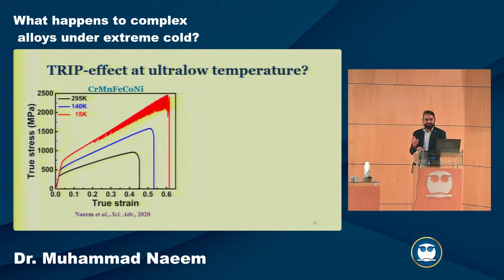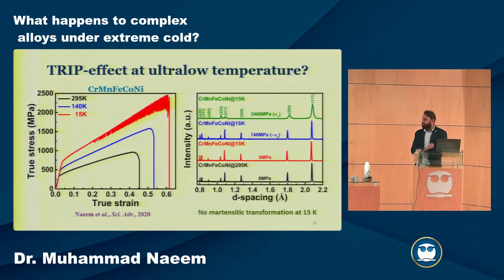So we did an in situ experiment with neutron diffraction at 15 Kelvin. And indeed we see an increase in strength, and also an increase in ductility, in the same alloy which they were working on. But when we look at the diffraction patterns, of course there are peak position changes, they become broader, their intensity changes, but we don't see any new peak related to a second phase coming out. So there is no phase transformation in this case. In this study, which we published about 4 years ago, the main thing was that there was something wrong with those calculations. They revisited them, and they had not included vibrational entropy, which plays a significant role at low temperature.